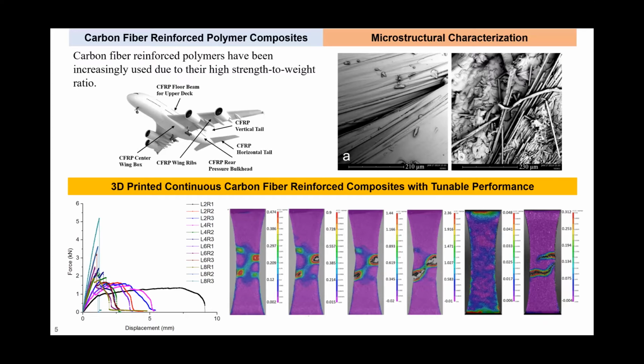So by using continuous carbon fiber, we can significantly improve the mechanical properties of the polymer composite, and especially further increase the strength to weight ratio. And here you can see from these SEM images, we can see these continuous fibers clearly. And the main objective of this approach is also similar to the first one. We want to further design and fabricate continuous carbon fiber reinforced polymer composite with tunable or tailorable performance.